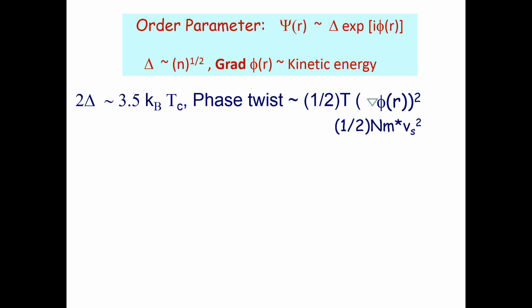Now we can destroy superconductivity in two ways. Either we can destroy the amplitude, basically the pairs, cause depairing, or we keep this intact and only break the phase. So the pairs are there, but they are not phase correlated. That will lead to the macroscopic quantum state being destroyed either by playing with this, or by playing with this, or playing with both. But what are the energy scales involved? If I take a bulk superconductor like niobium, the order parameter in the BCS limit is 3.5 k_B Tc. So this turns out to be the easiest way to destroy the superconductivity in bulk samples.